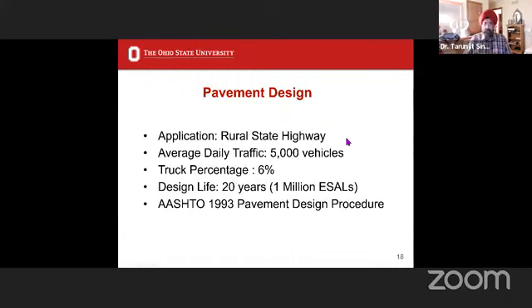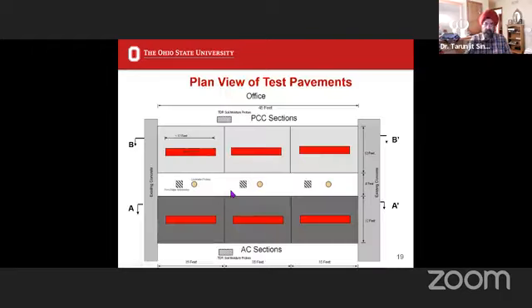We were looking at a state highway, and the design life is 20 years for 1 million equivalent single axle loadings. That's what we're looking at, 20 years. So this is how it was designed. In essence, if you can see, three sections of the concrete, the asphalt below. One section was kept as control for both of them. That is, no CCBs were used. The other two had CCBs in them. And the middle part of each of the tires.